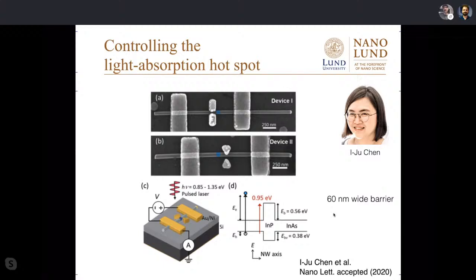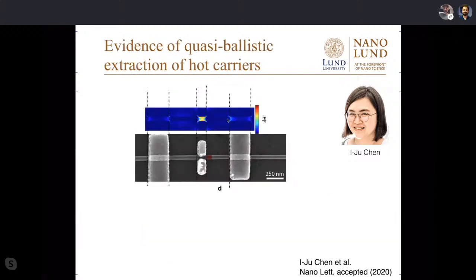The other thing you would like to do is to do this with light and actually control where the light is absorbed, not just hope that symmetry is broken somehow, but actually control light absorption. This can be done with plasmonic elements. So you use two metal structures that are separated by about 50 nanometers or so, and you can get strong light and electric field enhancement in this gap. So when you shine light on it, the light intensity will be strongly enhanced between these. And if you put them close to the barrier, which my student Yu Chen, now a postdoc in Copenhagen, succeeded with, then you can actually see what happens if you absorb light close to such a barrier.